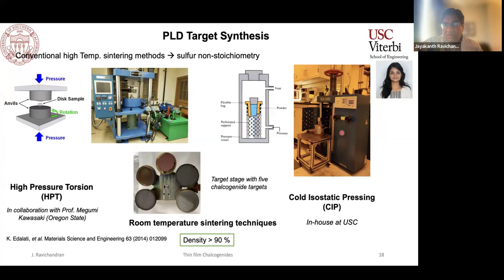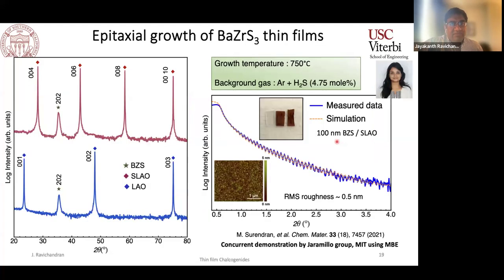Then my group acquired a cold isostatic press. This is almost close to 800 megapascal hydrostatic pressure, which allows us to sinter targets not as great as the HPT, but close enough to this number, which allows us to get a lot more targets at this stage for most of the sulfides that we are interested in.